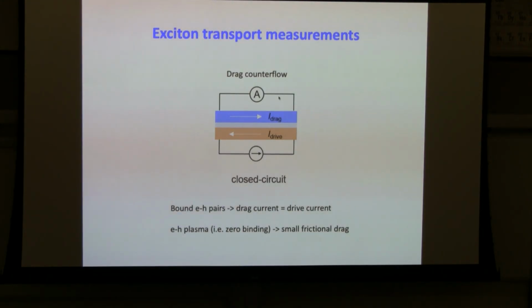Okay. So maybe the most direct experiment is to directly flow an exciton current in the system. In order to flow an exciton current, this is what we do here. Remember that we actually have independent electron contact and hole contact to each of these layers. So what we do is we drive a current in the electron layer, and we measure the current in the hole layer. And this is called a drag counterflow measurement. If you have excitons, bound electron-hole pairs, the amount of current that you drive should be equal to the amount of current that you drag in the system. So the drag current should be equal to the drive current, except that the two currents are now flowing in opposite directions. So overall, you don't get a charge current in the system, but you get something flowing, and that something is the excitons flowing in the system.